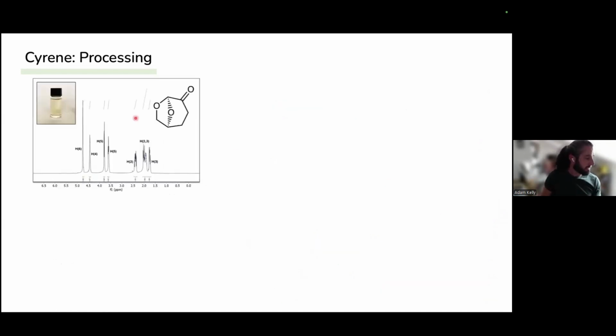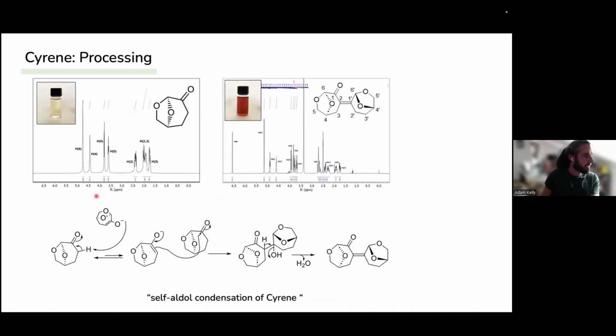So to analyze what these compounds were, we did NMR. This is NMR of a clean cyrene spectrum. And this here is NMR then of this red cyrene degradation component. And then through some wizardry known as a COSY spectrum, Marta Corvu here at CINEMAT was able to deduce that this is what the compound looked like that cyrene is degrading into. So this is known as a self-aldol condensation of cyrene, and typically you need a base to start this reaction, but in this case we're actually able to induce it by heat, and this is the dissolved solid that we find mixed in with the cyrene in here.